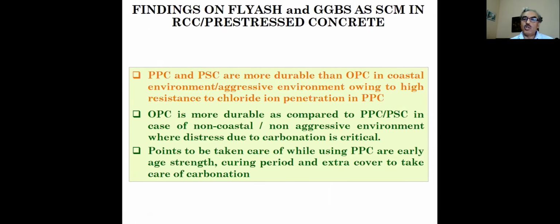PPC and PSC are more durable than OPC in coastal environments and aggressive environments, owing to high resistance to chloride ion penetration. When we put fly ash or slag, the resistance to chloride ion penetration increases significantly. OPC is more durable as compared to PPC in case of non-coastal, non-aggressive environments, where distress due to carbonation is critical.